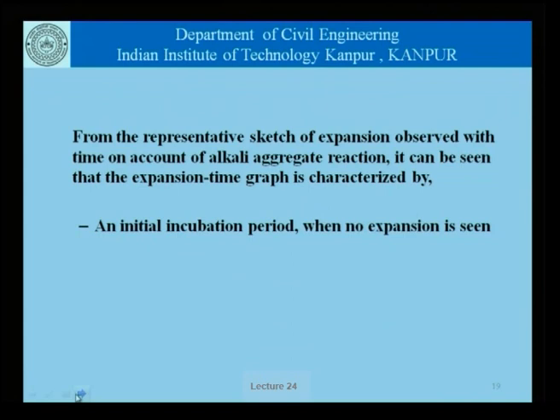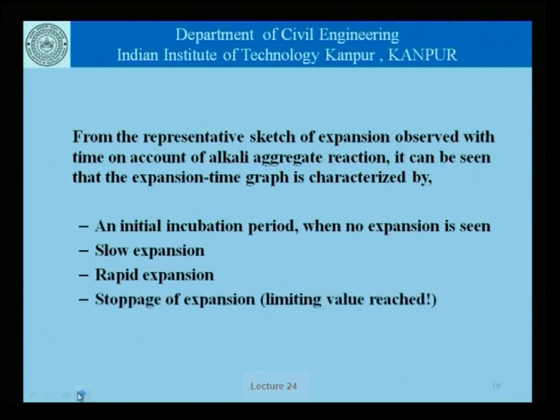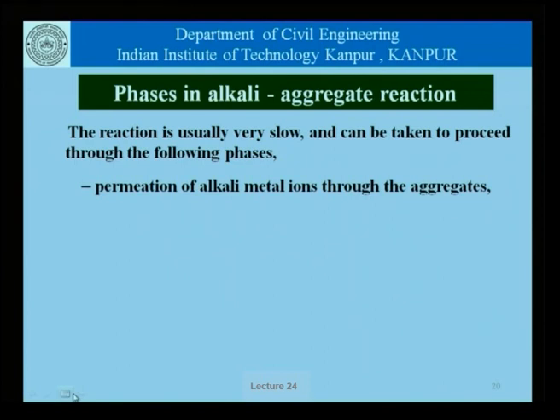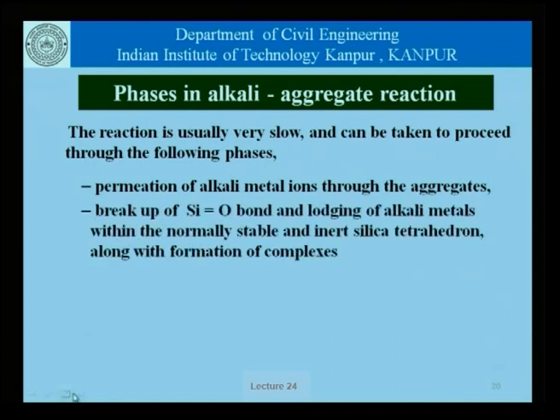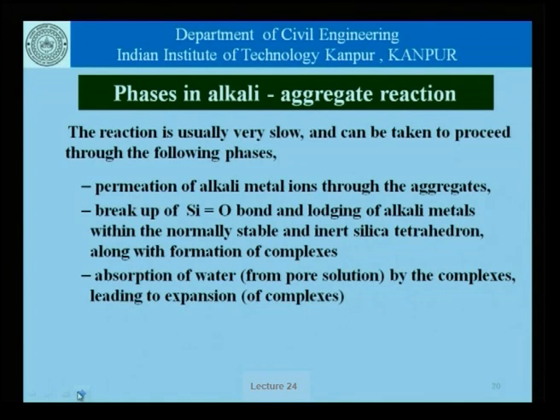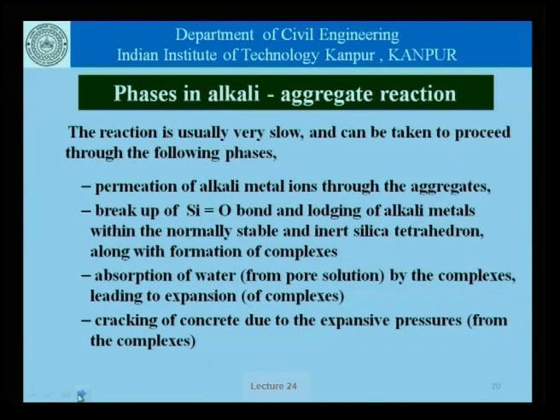From the representative sketches of expansion observed with time on account of alkali aggregate reaction, it can be seen that the expansion-time graph is characterized by an initial incubation period when no expansion or very little expansion is seen. The expansion begins to pick up; there is slow expansion to begin with, then the reaction enters into a rapid expansion phase, and finally the expansion stops with some limiting value being reached. Physically, this process follows the following phases: permeation of alkali metal ions sodium and potassium through the aggregates; break-up of the silica bond and lodging of alkali metals within the stable silica tetrahedron along with formation of complexes; absorption of water from pore solution by the complexes leading to expansion; and finally cracking of the concrete due to expansive pressures.